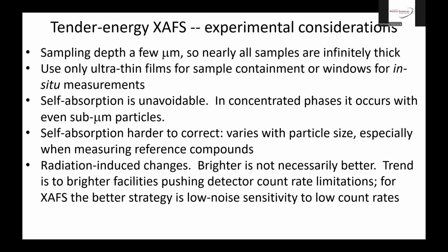There's also a fairly common problem with radiation-induced changes, especially to sulfur oxidation state, for example. At lower energies, more of the power of the beam is deposited right in the sample as you're analyzing it. And so you're more likely to have radiation-induced redox changes. And so brighter is not necessarily better, although the trend of facilities is to make things ever brighter and push the detectors to count higher count rates. I always raise my hand and say, that's not always best.